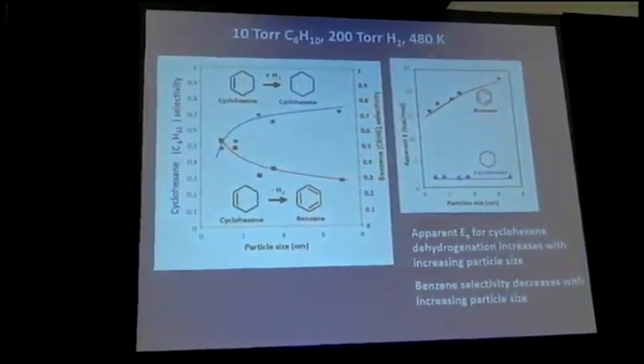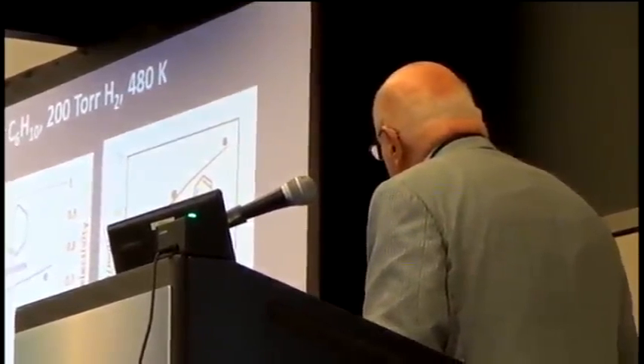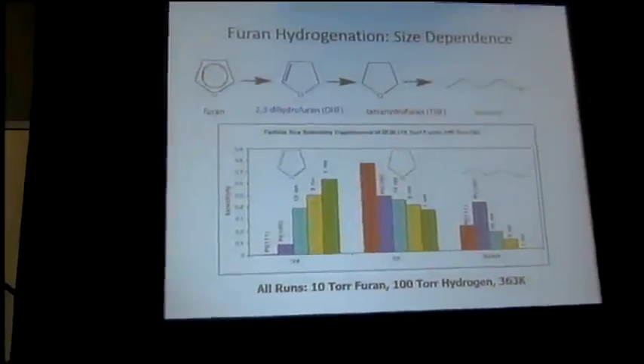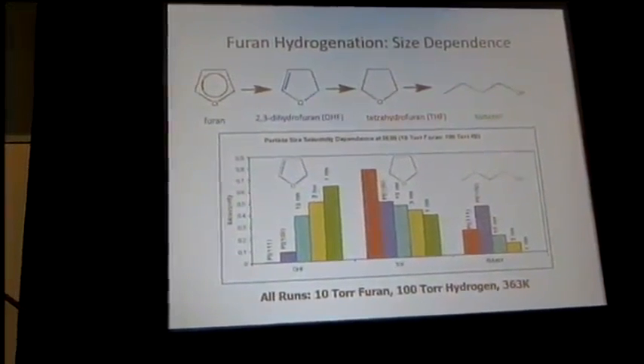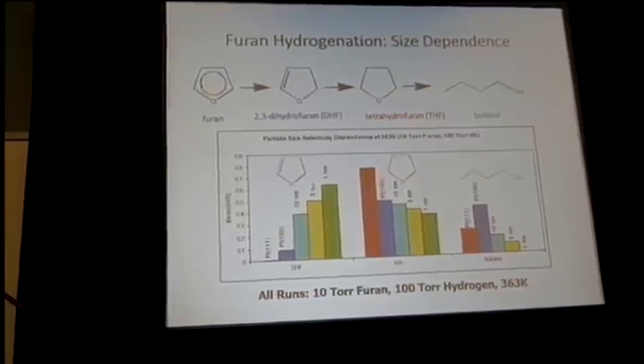And so what you find is that as you change the size, this is benzene cyclohexane hydrogenation to dehydrogenation selectivity. You make cyclohexane by hydrogenation at large sizes, and you make benzene at smaller. You make benzene here, which is small particles like to dehydrogenate. The big particles like to hydrogenate. You take furan, you see partial hydrogenation, and as you change the size and the crystallography, you change the product distribution from one product majority to another product majority.